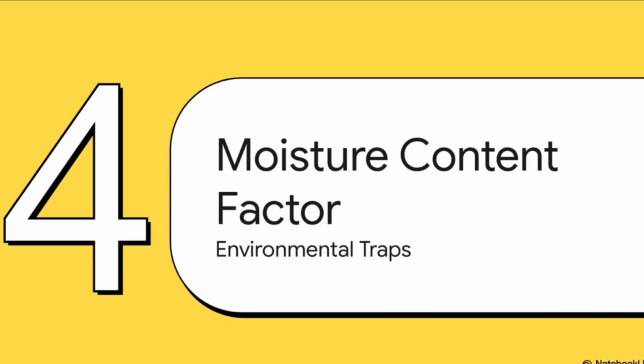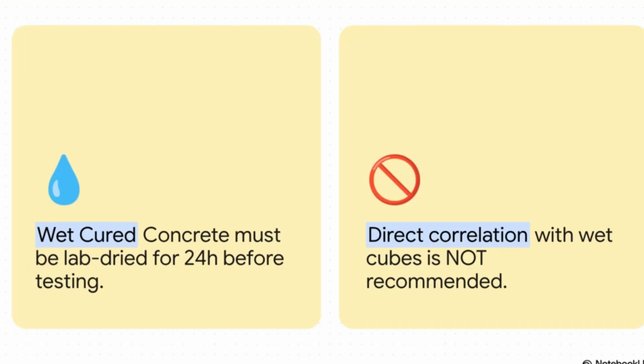Next up is Section 4, the moisture content factor. Now let's look at how moisture can totally trick the hammer. Say you have wet-cured concrete test specimens. You can't just pull them out of wet storage and test them right away. Nope, the standard requires them to be kept in the laboratory atmosphere to dry out for about 24 hours before testing. Attempting to directly correlate rebound numbers taken on a wet cube with the compressive strength of that wet cube is strictly not recommended. Water trapped inside the pores of the concrete fundamentally changes the surface hardness, which totally changes the resulting bounce.